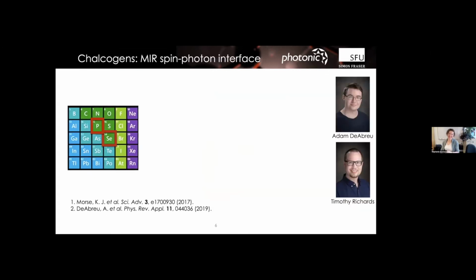But we did. So we started first looking, admittedly, we relaxed one of our axioms. We started looking at the mid-infrared rather than telecom, because we weren't aware at the time of any telecom opportunities. We were looking for something that had a stronger quantum efficiency, and what I mean by quantum efficiency, for those of you who aren't in this space, is the proportion of the time that when the object is in the optical excited state, it spits out a photon, roughly speaking. So if it spits out a photon like every time, that's a very, very high quantum efficiency. And that's the kind of object you want to have, because it means there's not non-radiative processes that are going to get in the way of any kind of strong interaction with light.